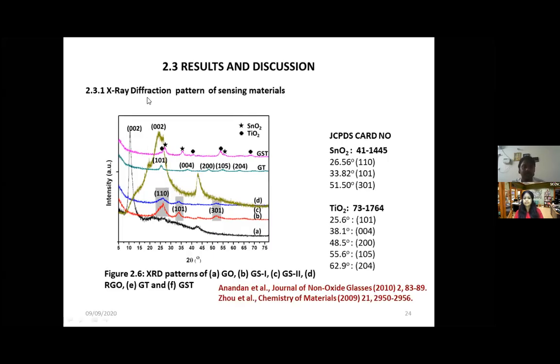The first one is the X-ray diffraction pattern. The black curve here is associated with graphene oxide peaks. We have a separate lookup table, and these values can be seen in the literature as well. This is the 2 theta value here. For example, if there is a peak at a particular point, it is associated with the 002 plane. So we look up the JCPDS card number or the existing literature, and it is matched to those particular peaks.